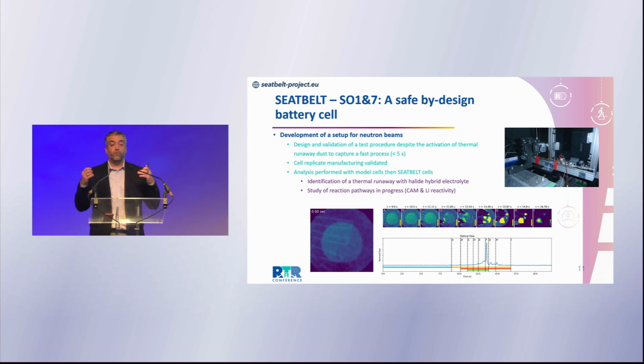And basically what we are provoking is to melt lithium metal and look also where are the failures and what lithium metal melting can induce in terms of failures to the subsequent materials. Is there onset of reaction, etc. So here, the so-called tour de force of this experiment is that with a very fast camera, we are able to capture the lithium metal and the degradation of the battery.